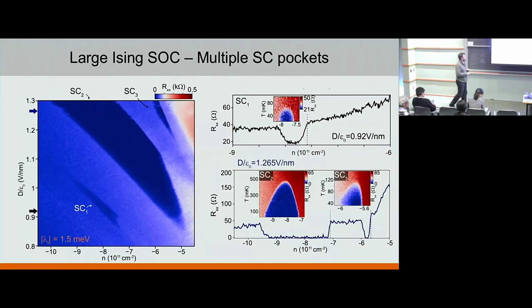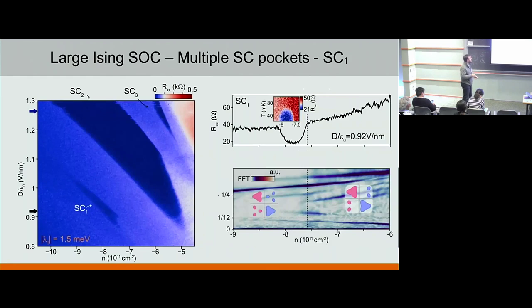So first I will very briefly mention SC1. Again, as a reminder, this is the superconducting pocket here. If you do this experiment trying to figure out the Fermiology where SC1 happens, it happens close to this transition where you have essentially two big pockets, three small pockets, and two big pockets and two small pockets, okay? So it's definitely on this side.